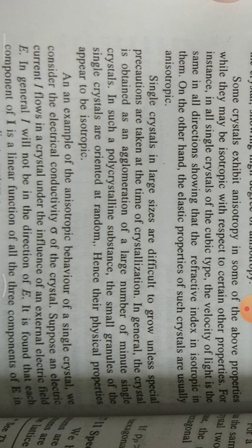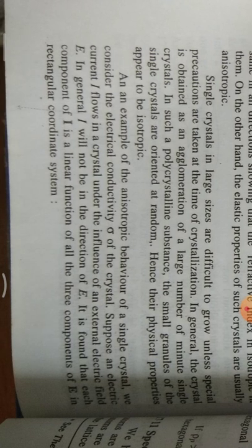Some crystals exhibit anisotropy in some of the above properties, while they may be isotropic with respect to certain other properties. For instance, in single crystals of the cubic type, the velocity of light is the same in all directions, which shows that the refractive index is isotropic in them. On the other hand, the elastic properties of such crystals are usually anisotropic. Large single crystals are difficult to grow unless special precautions are taken at the time of crystallization.